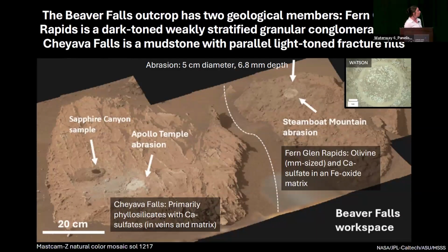So here's the actual outcrop where we did the experiment. As you can see here, this is the Steamboat Mountain abrasion patch. We also have Apollo Temple and Walhalla Glades more towards the south that we're going to talk about later in the presentation. And essentially what we see here is that the Steamboat Mountain abrasion outcrop here at Beaver Falls is olivine bearing. It has an iron oxide red matrix and calcium sulfate. So that's a weakly stratified granular conglomerate that's dark toned.